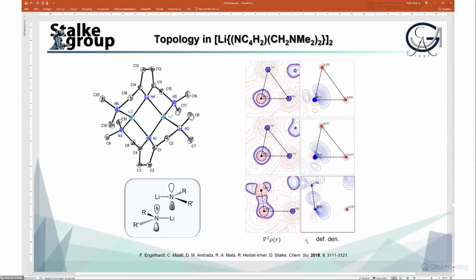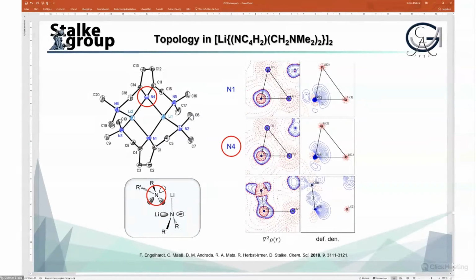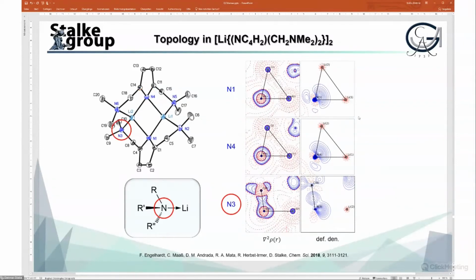So what we look at in the residual density and the Laplacian, the deformation density, we have to separate N1, where we have the lone pair, the residual density, more counted towards lithium-1 than lithium-4. This is almost on the bisection, ideally on the bisection, and this is pointing towards lithium. These changes, of course, the differences are minute, however, they are there. So this is minute chemistry anyway.